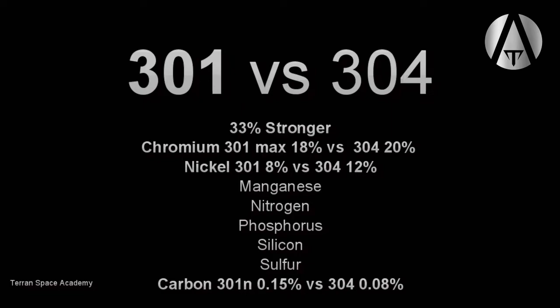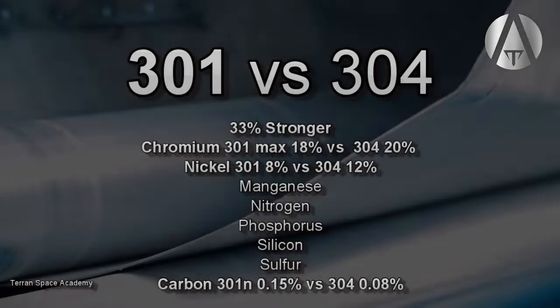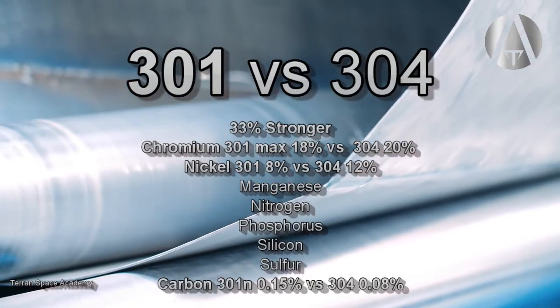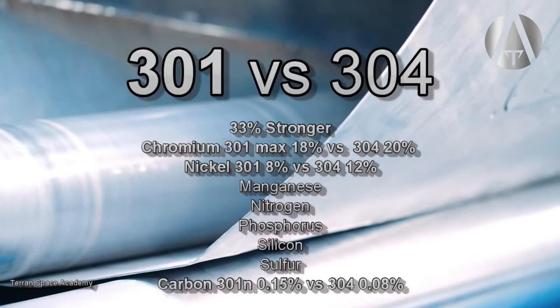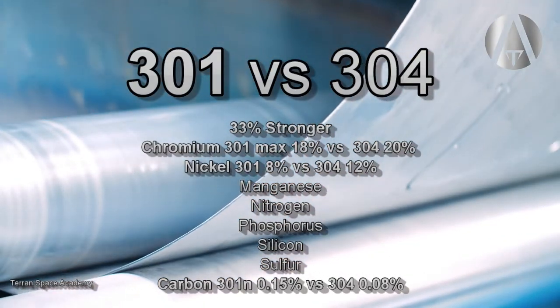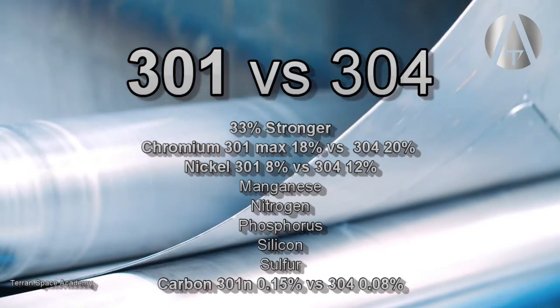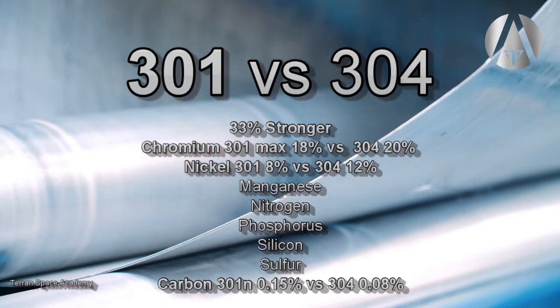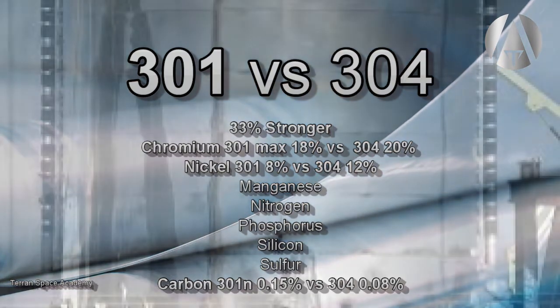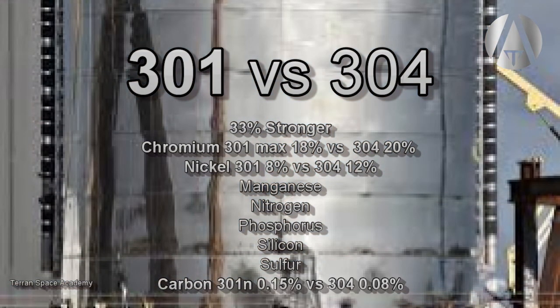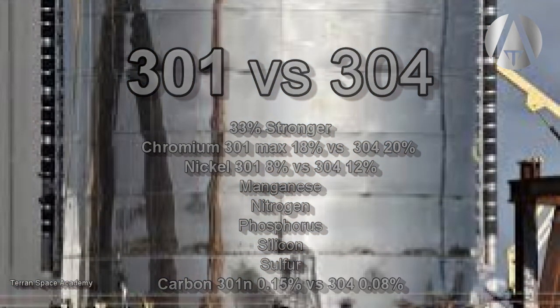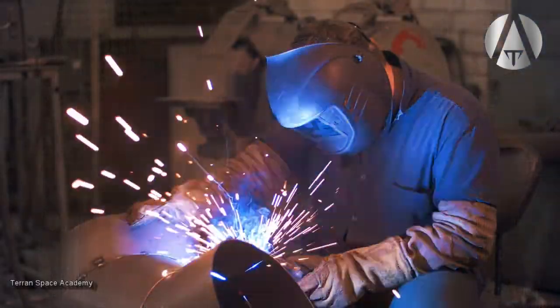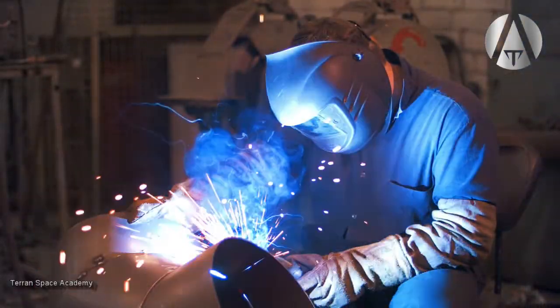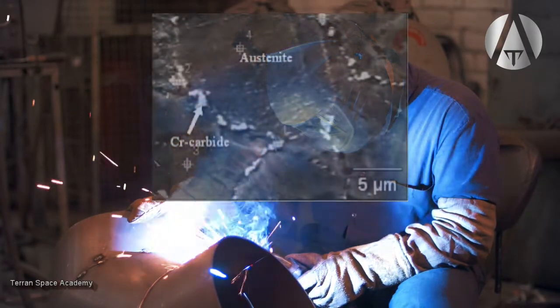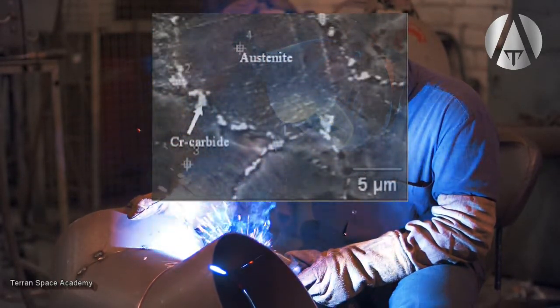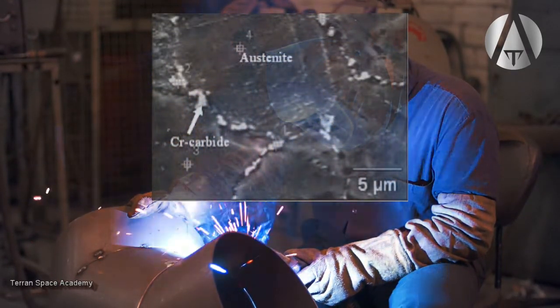At normal temperatures and in a mildly corrosive environment, there is little difference between the two alloys related to corrosion. The lower chromium and higher carbon in the 301, however, make it a little more susceptible to corrosion. If you weld a piece of 301 steel, you will see some corrosion starting in the weld lines very quickly. This is because the chromium in the steel combines with carbon in the steel when welded to form particles of chromium carbide that deplete the chromium in your alloy and weaken your Starship at the weld line.